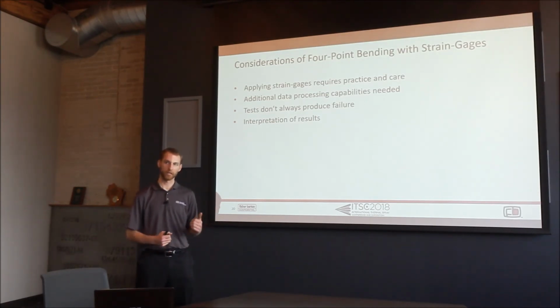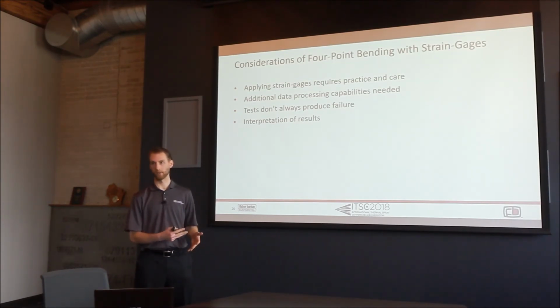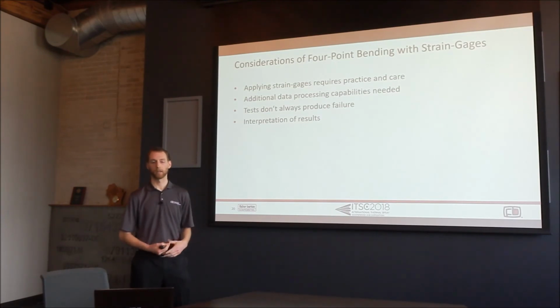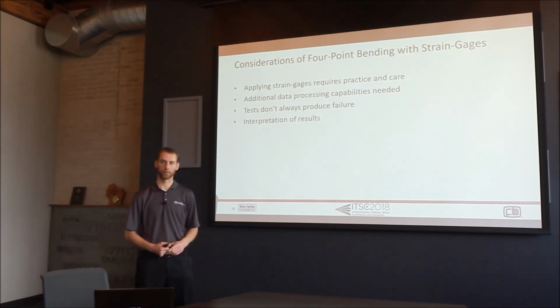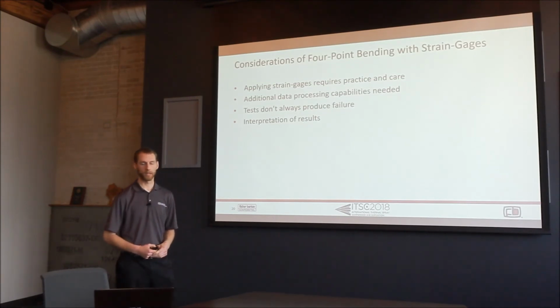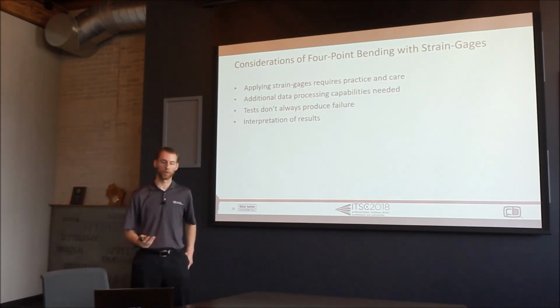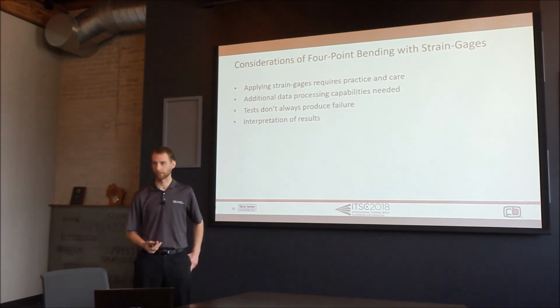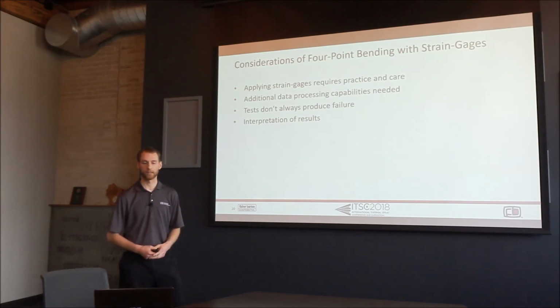And as I've shown here, the tests don't always produce failure. There's going to be a relationship between your substrate material, when that yields, and what the coating can withstand. In those 3 examples, we didn't show complete adhesion failure. Using strain gauges also opens the door to further interpretation of results. It's not just spitting out a number, but you're really looking at the behavior of the coating overall. That does require some expertise in the test and in the system that you're working with.